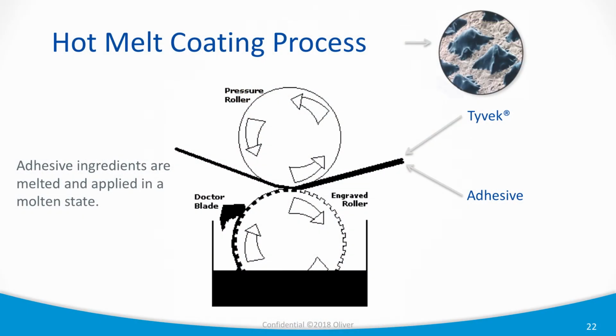So Rick talked about earlier on two different adhesive technologies, the hot melt and the air knife coated. I'm going to just talk about hot melt real quick. So that's the picture in the upper right corner. Those blue dots are basically what Rick was talking about. We're printing or laying down dots of hot melt adhesive onto, in this case, medical grade Tyvek. You can see the fibers of the Tyvek in between the blue dots. So basically it's just depicting here almost like a gravure type cylinder, laying down those micro dots. There's a doctor blade that is scraping off the excess adhesive off of the cylinder before we're laying down those dots onto the substrate. So that's an animation.